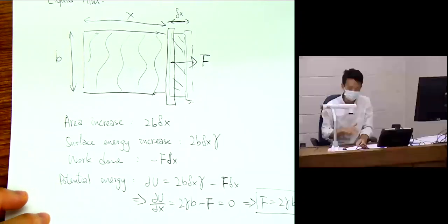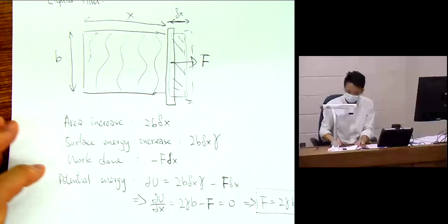But heating up the glass and then doing that experiment was not easy at that time. It's also not very easy now. Okay, because you heat up to about 800 degrees and everything gets complicated when you're at high temperature. So the agreement was not very good. It's close, the same order of magnitude, but maybe 50% off. Okay, so we don't want to diminish any of that contribution. It's still a great experiment.